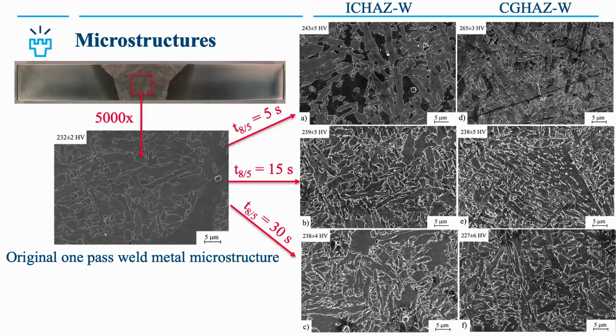And what we can see, mainly it is still acicular ferrite. And we can also see, as a reference, we have hardness values here. We can see that in the coarse-grained heat affected zone with 5-second cooling time, the hardness slightly increased. But in other cases, it is more or less the same, so there is not much variation. And we can also see that when we have these grain boundary ferrite regions here, they are still present after the heat affected zone simulation, like here, for example.